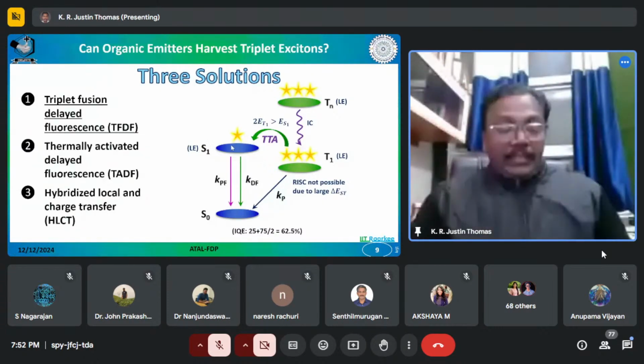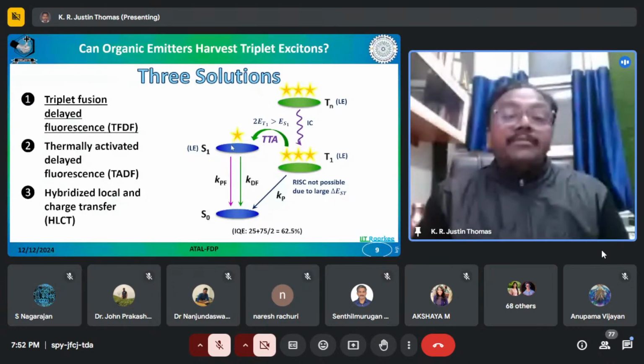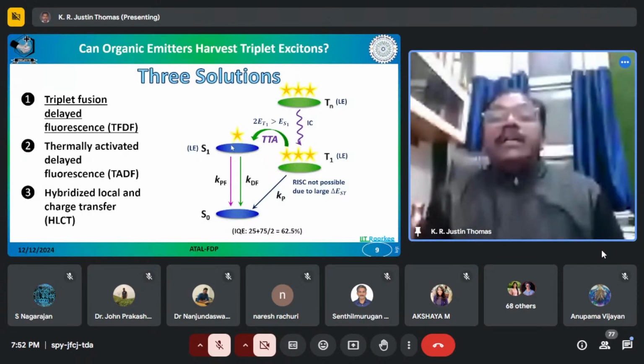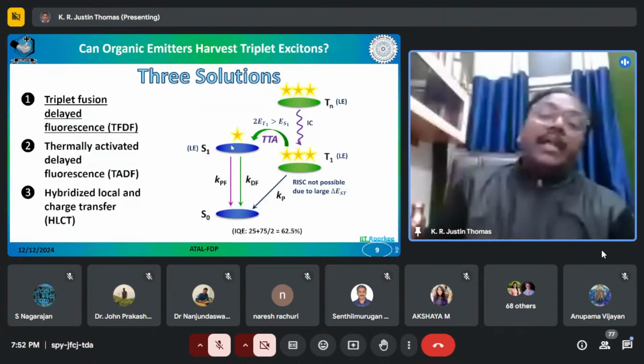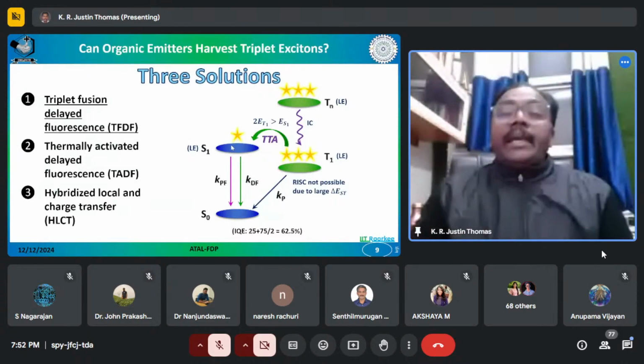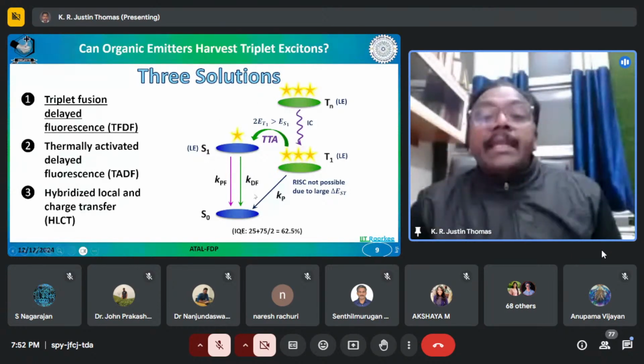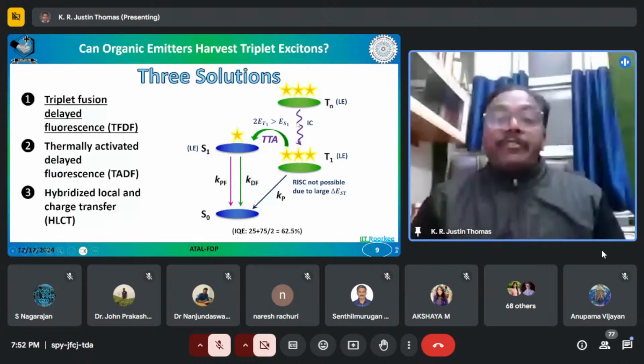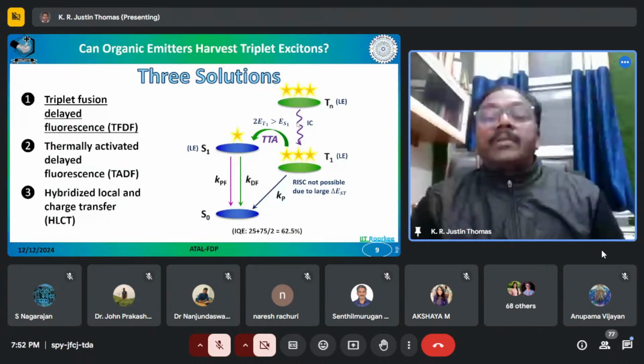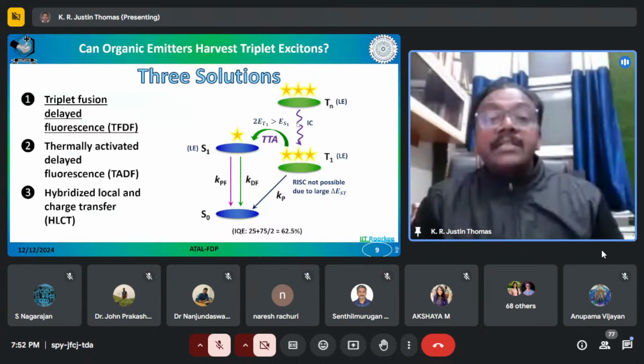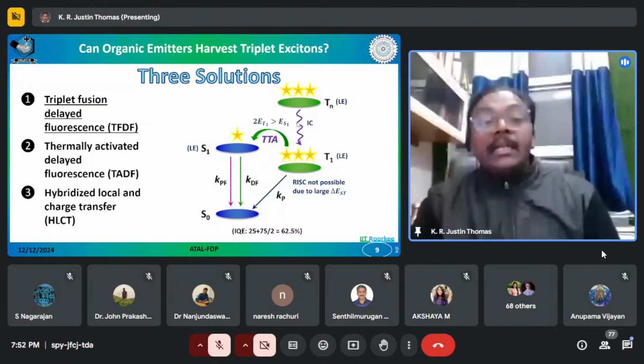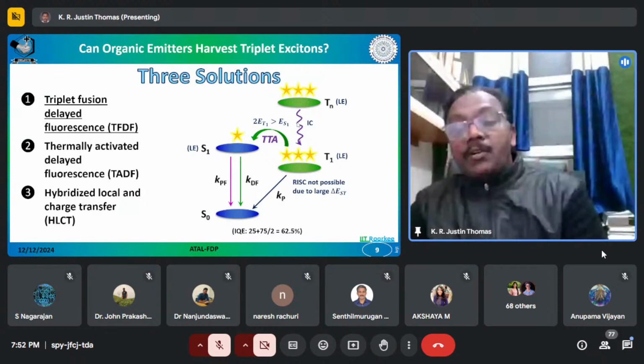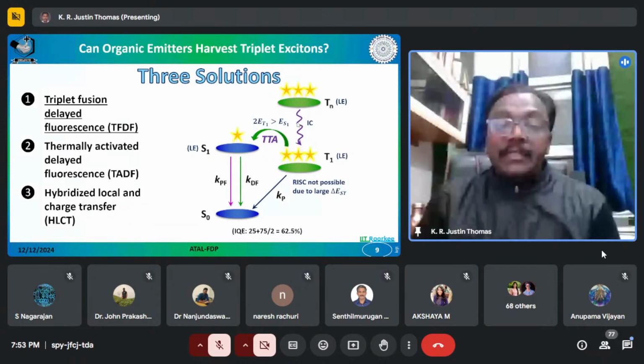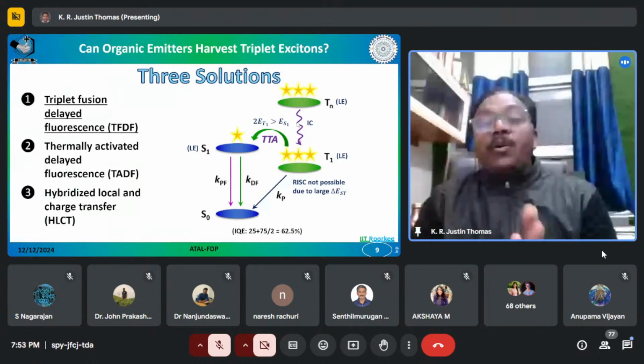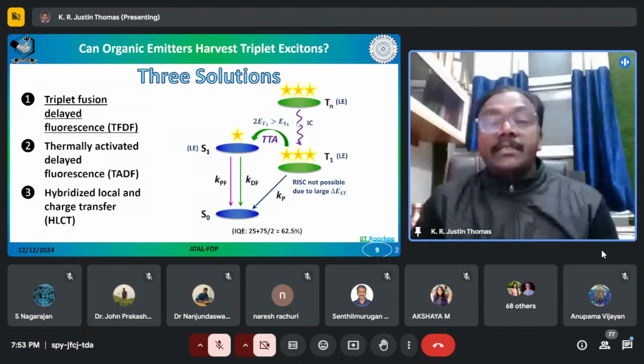So that means that when triplet excited states collide with one another, that is called a TT annihilation process. It can relax to a singlet excited state and a singlet ground state. So one is relaxation, another is an up conversion. Okay, so this can be shown in the Jablonski diagram, something like this. So as I have told, in this phenomenon, two triplet excited states will be converted to one singlet excited state and one singlet ground state. So one of the triplet excited states is lost to the ground state. One is retained, converted into the singlet excited state. So out of the two triplet excited states, you will get only one singlet excited state.